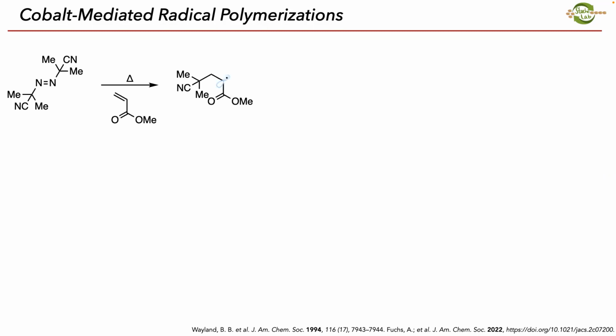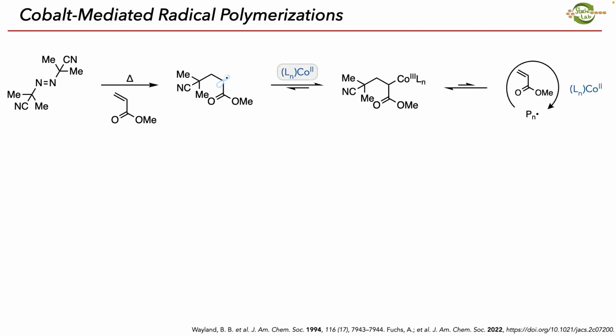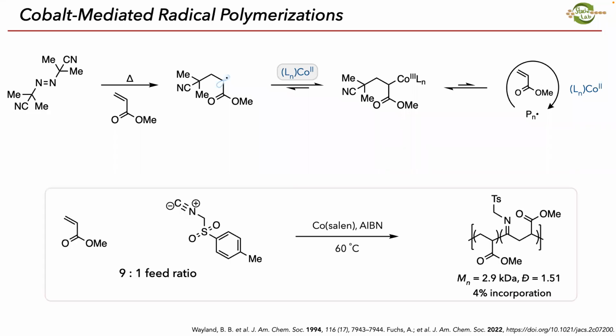So typically the way this is done is we take AIBN and methyl acrylate monomer, we heat this up, it starts generating these radicals shown here. These will couple with a cobalt-2, so these two join together, and you get a dormant species, which doesn't do anything. So this species right here is inert, and then once we reach enough of this, this will enter into an equilibrium where the chains can continue to grow and propagate and become longer.